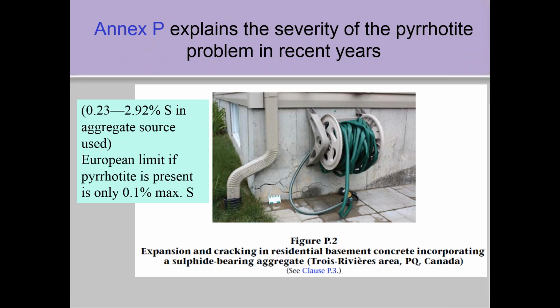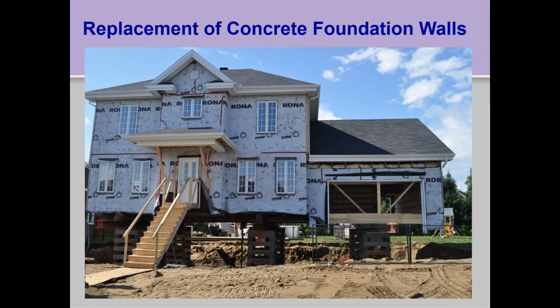That's an example, a picture out of Annex P showing a foundation, the cracking in the foundation of a house that's only about 2 or 3 years old in Trois-Rivières. And it can happen with 1 or 2% of the sulfide sulfur in the aggregate. The Europeans have a limit of 0.1% sulfide sulfur if it's pyrrhotite. And they've had to raise over 100 houses. It came from one quarry near Trois-Rivières, and these are brand new homes. They basically had to raise them up, remove the foundations, and replace the foundations.